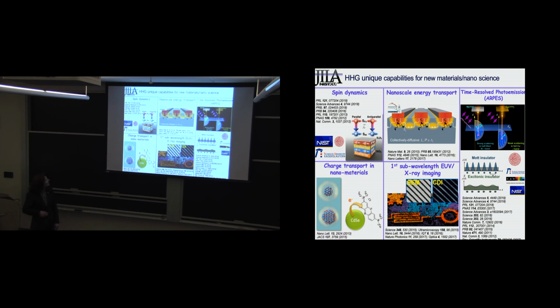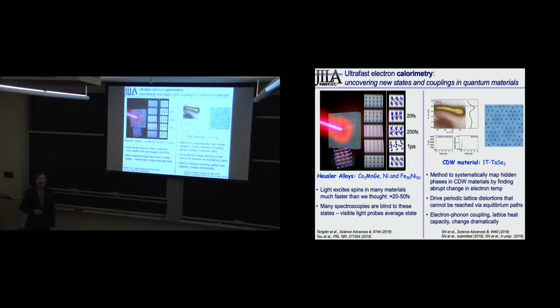In fact, we developed a technique that, as somebody who's been in ultrafast science for a long time, our community should have figured out sooner. We call it ultrafast electron calorimetry. For those of you who use ultrafast lasers, you know that if you shine a laser, let's say on a metal, the electrons will heat up very quickly because their heat capacity is less than that of the lattice, and then they'll undergo electron-phonon scattering, the electrons will cool and the lattice heats up. And because of the disparity in the heat capacities, you can heat the electrons to thousands of degrees Kelvin, while eventually when they cool down, the lattice might only be heated by 5 to 10 Kelvin, so you don't damage the material.